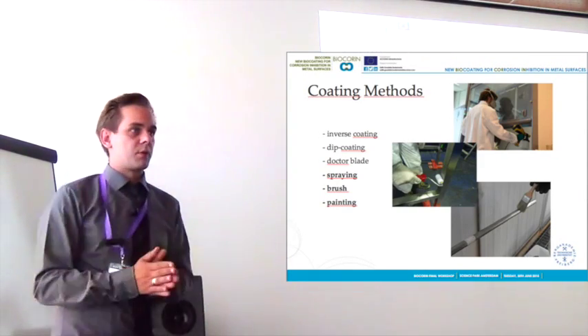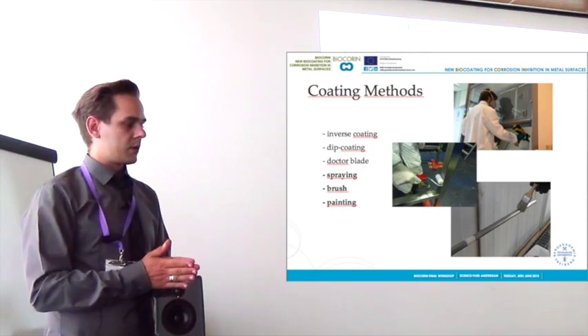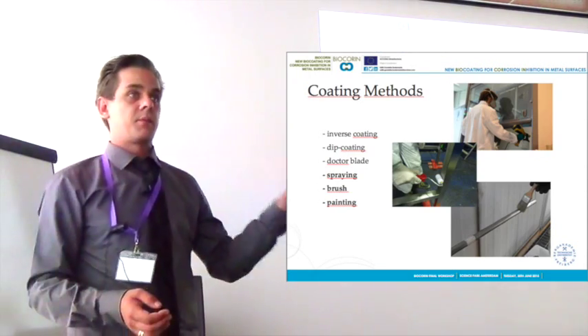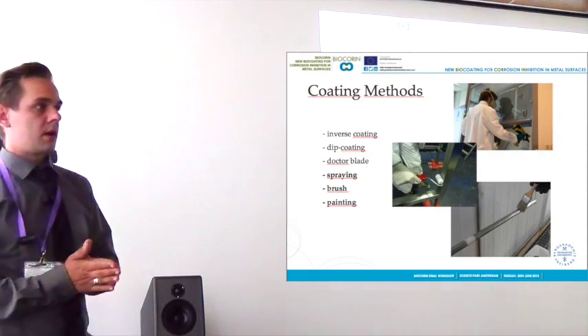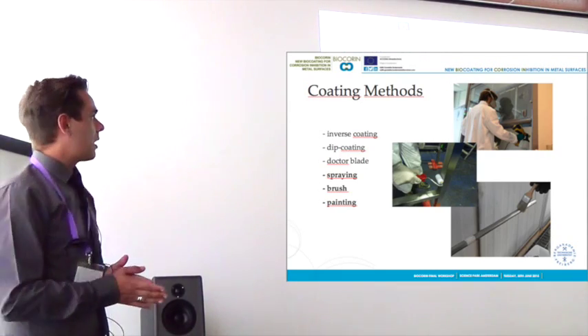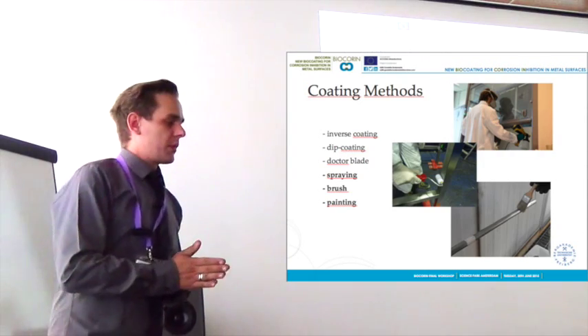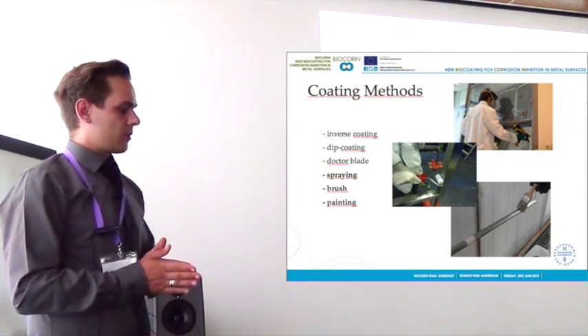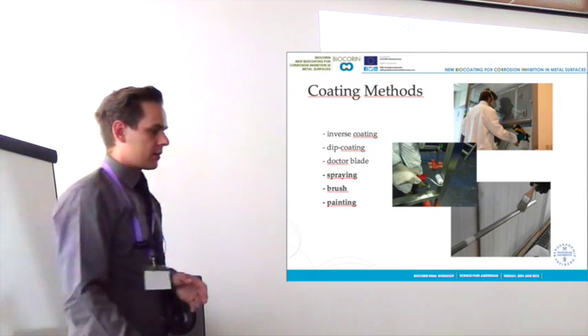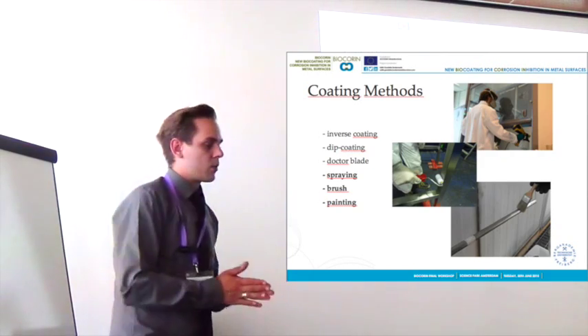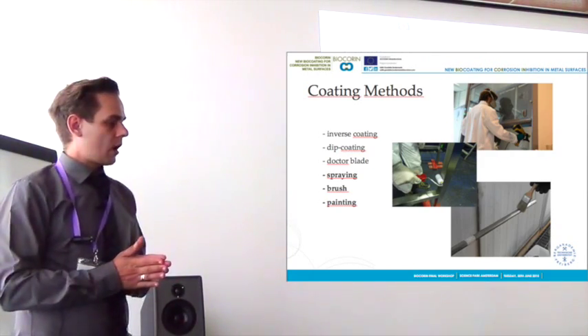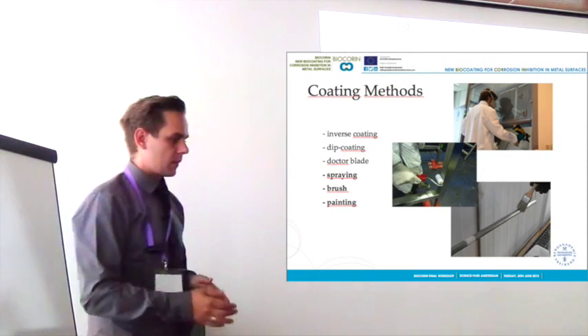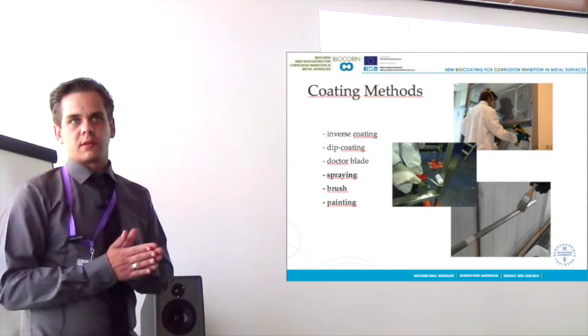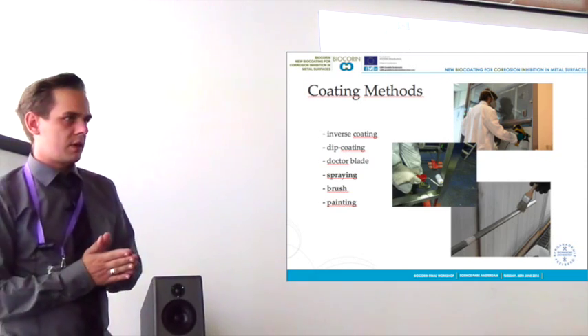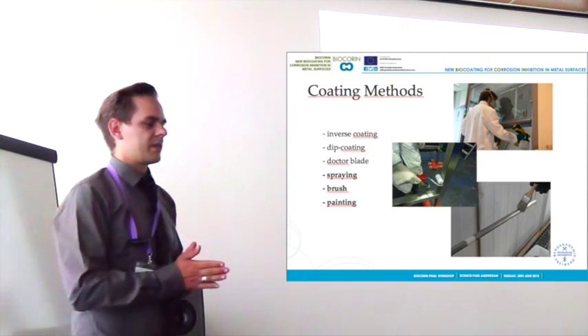As coating methods in the laboratory, often used are inverse coating, dip coating, and doctor blade. This was what we used at the beginning of the project, but as the project moved on, we tried to upscale our coating methods to methods that are more interesting for the industry. So we use spraying, brush, and painting most of the time. Those are some images from the laboratory where we prepared the structures for the demonstrator. Spraying and painting was the most suitable method for the industry process. Brushing was possible as well, but wasn't that easy.